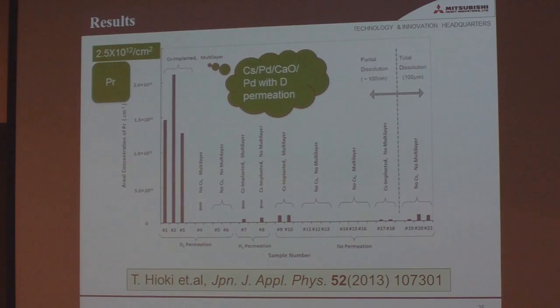See, if the effect is due to the flux, if you've got a gas source, your flux is not very large because the pressure is not so high. If you have an electrochemical loading, you can get higher pressure and higher flux. So do you monitor the flux through the gas output on the other side? Can you compare the difference in flow rate between gas and electrochemical that way?